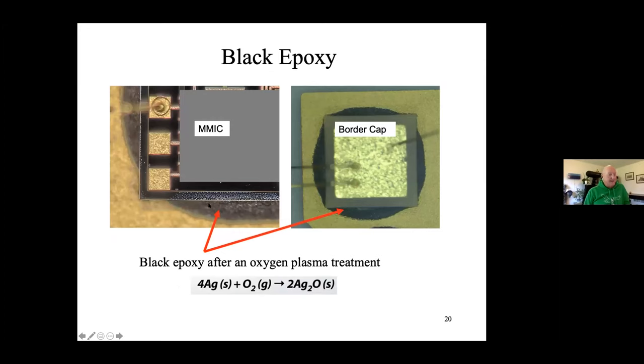Now, if you invoke that after your silver die attach, well, then you're gonna turn the epoxy black. You can see here, it looks real black and looks terrible. So what? I guess is the name of the talk. But black epoxy, it's when you first go into the plasma cleaner, the oxygen plasma will ablate away the organic, and then you're gonna oxidize the silver flake. It's 70% silver flake. So below like 200 degrees C, you're gonna form this oxide of silver, which is black in color.